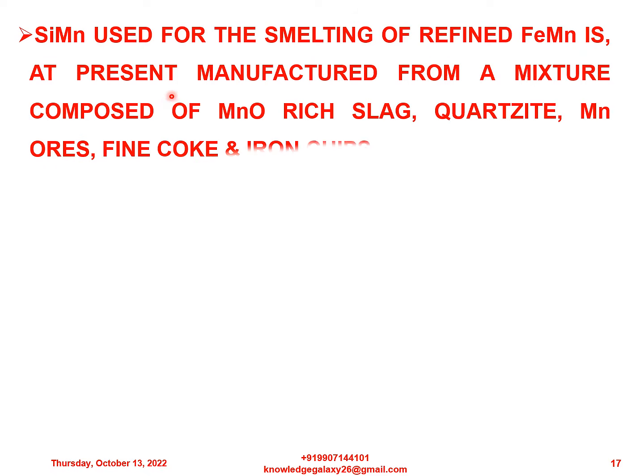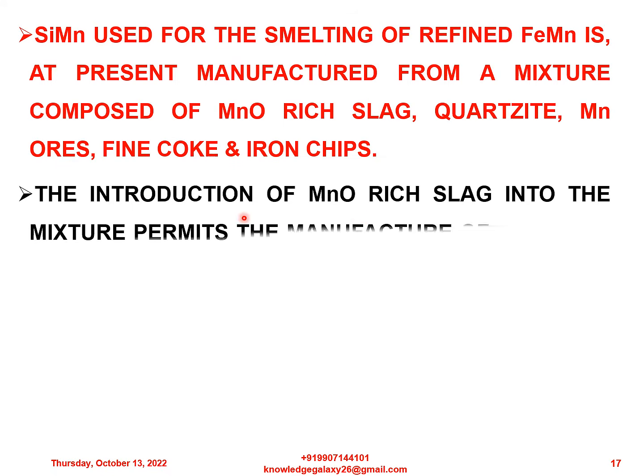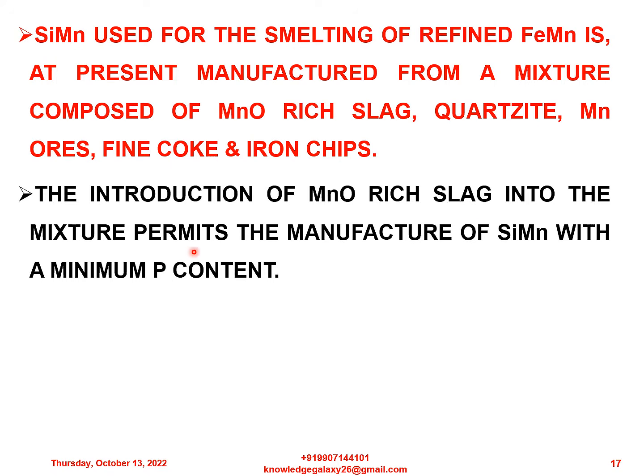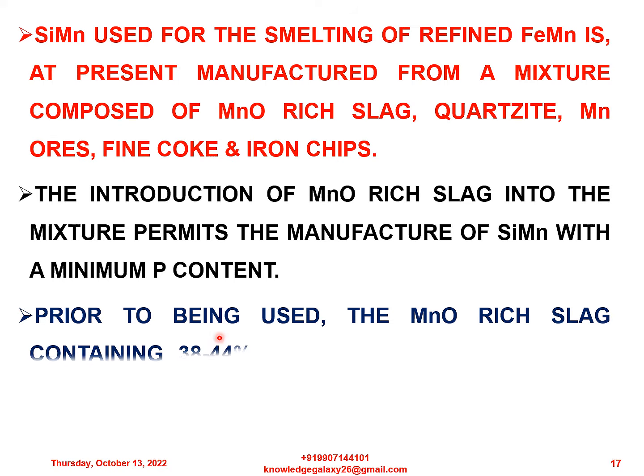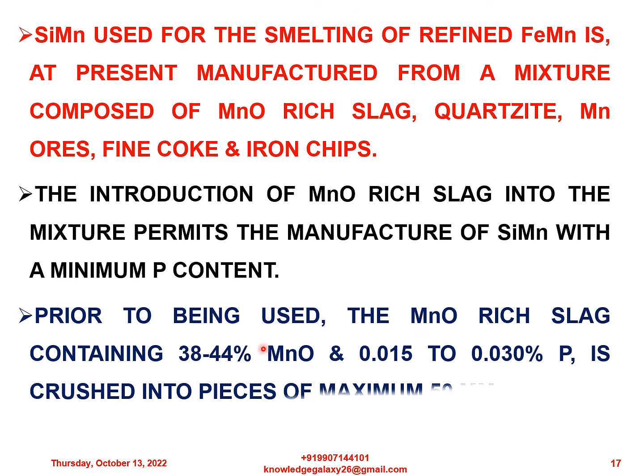Silicomanganese is used for the smelting of refined ferromanganese, at present manufactured from a mixture composed of manganese-rich slag, quartzite, manganese ores, fine coke and iron chips. The introduction of manganese-rich slag into the mixture permits the manufacture of silicomanganese with a minimum phosphorus content. Prior to being used, the manganese-rich slag containing 38 to 44% manganese and 0.015 to 0.030% phosphorus is crushed into pieces of maximum 50 mm size.